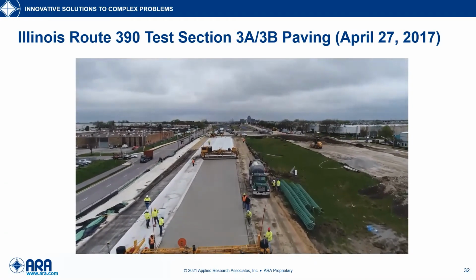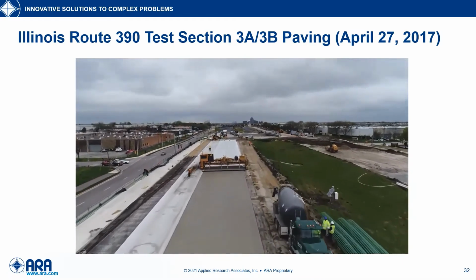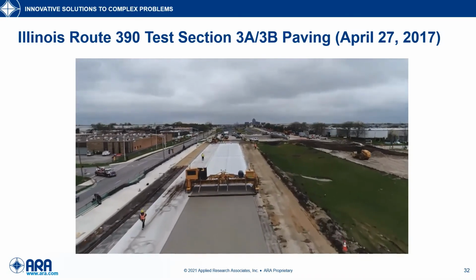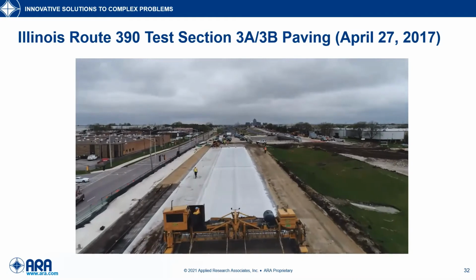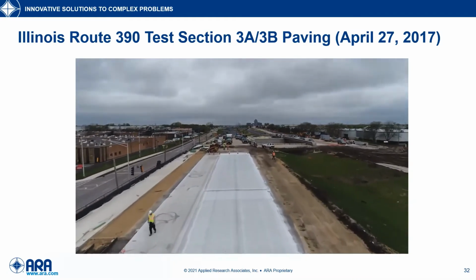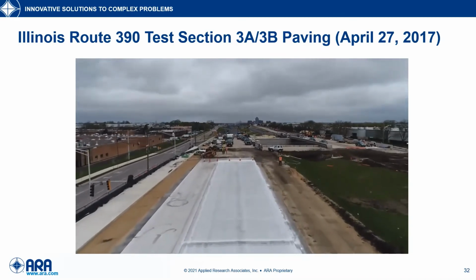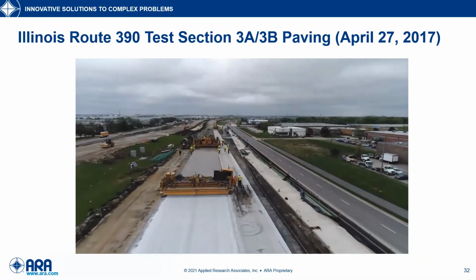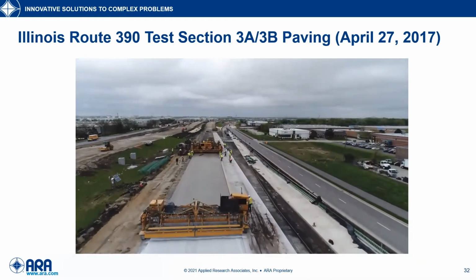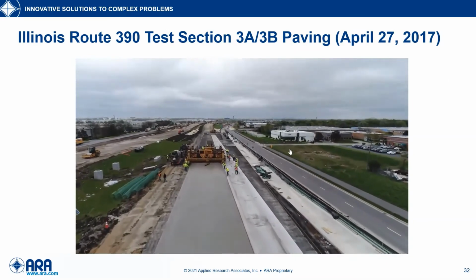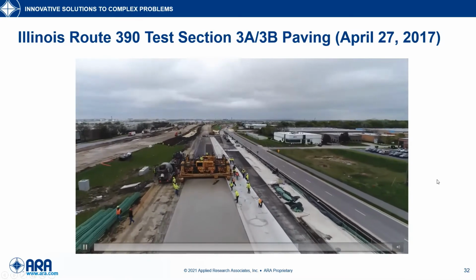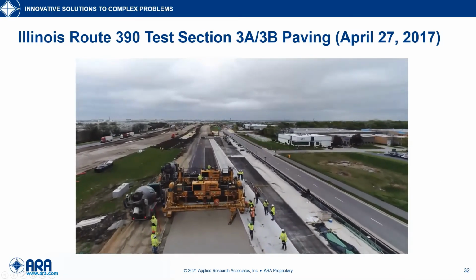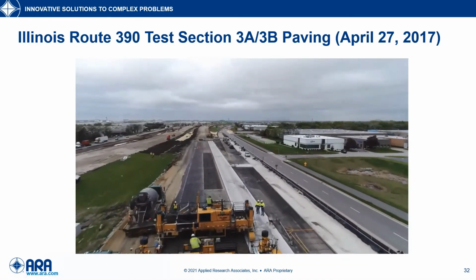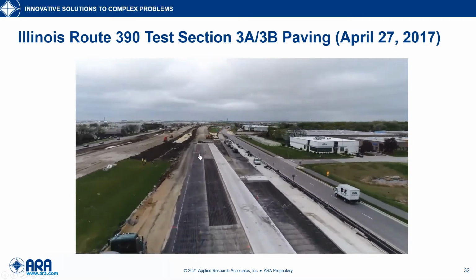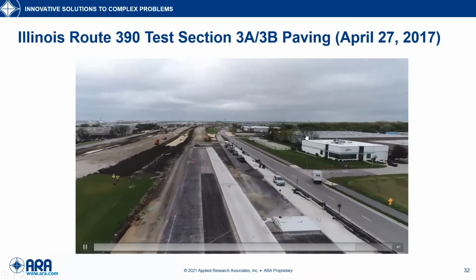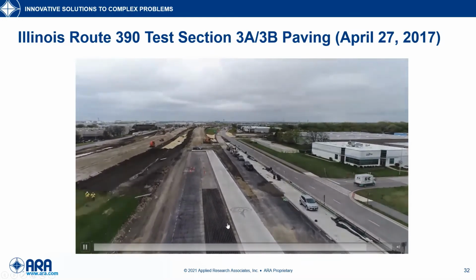We used uncoated reinforcement where we would usually use epoxy coated. Here the contractor is paving the internally cured mix 2 lanes wide using a placer spreader and paver followed by the curing machine. We used a different internally cured mix for each of the 500-foot sections. The section being paved here had macro fibers. Some of the other unique features: there's an end treatment here, which is a different design from the typical lug system or wide flange beam. And finally, as we get to the end here, you can see these cones, and those are the locations of the various sensors that were embedded in the pavement.